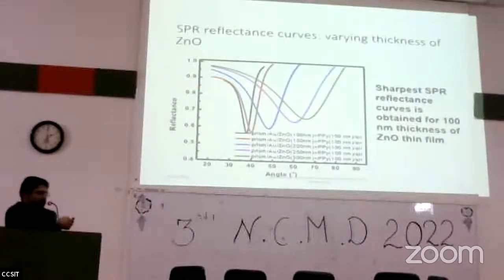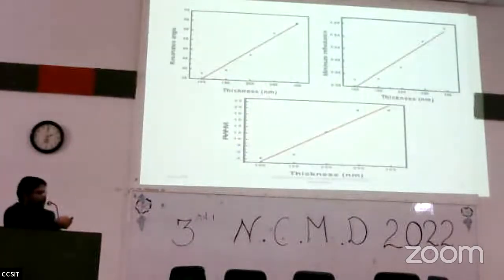Then we kept the thickness of polypyrrole fixed at around 100 nanometer and varied the thickness of ZnO. You can see again there is an increase in resonance angle, and the minimum reflectance goes on increasing. Then we take separate plots of this thickness variation with resonance angle, minimum reflectance, and full width at half maximum. It is easily predictable here that it is increasing with thickness. So for the minimum full width at half maximum value, this is our sharpest curve. So we optimize the thickness of ZnO as 100 nanometer.